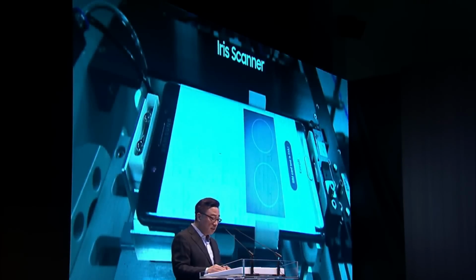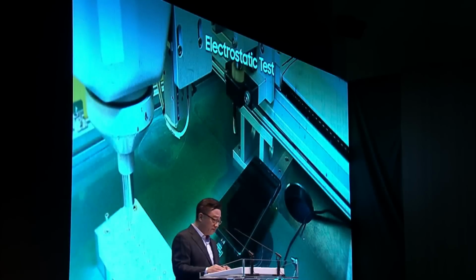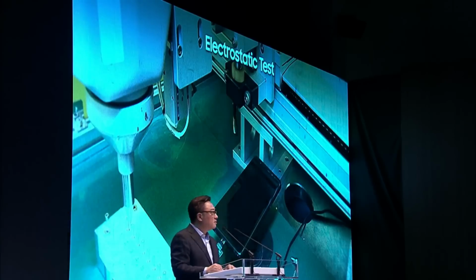To determine whether the newly introduced iris scanner had any impact, we tested to see whether an active iris scanner had a significant effect on electrical current use. We also subjected the USB Type-C port to a more than 4,000 volt electrostatic discharge to check whether USB Type-C was related to the incident.